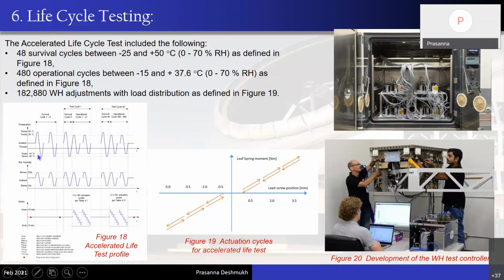That is shown over here. So when you're changing the temperature, you're changing the humidity. So we conducted such 48 survival cycles at different intervals of time. As you can see, each of these test cycles starts with one survival cycle followed by 10 operational cycles. And in total, we conducted 480 operational cycles, which are from -15 to +37 degrees. And these are recreating the conditions during the operation of the telescope along with the humidity which it will experience.